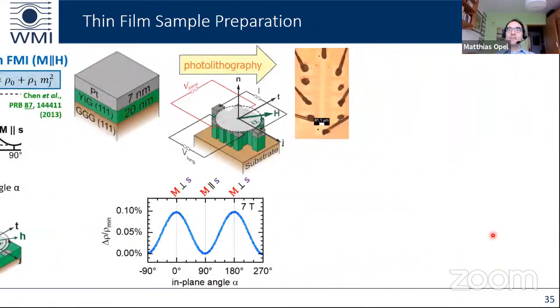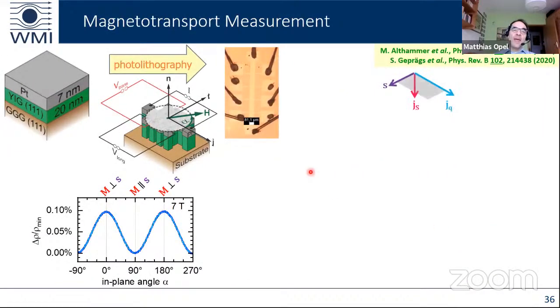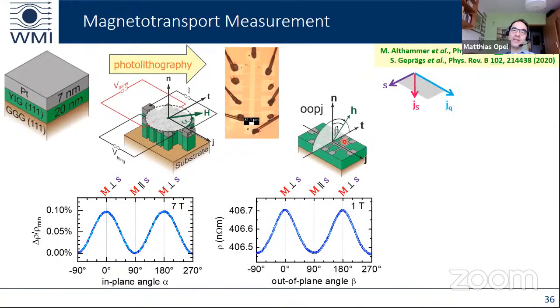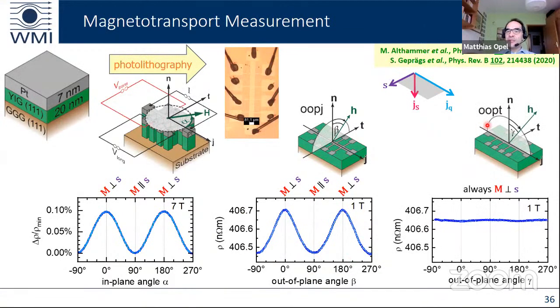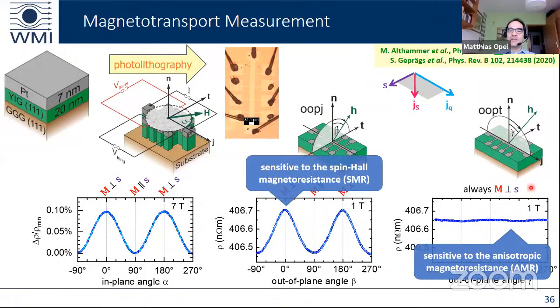Now, we can also rotate the magnetic field not in plane, but out of plane, perpendicular to the current direction, and we see the very same. We can apply the magnetic field out of plane perpendicular to the transverse direction, and there we see nothing. We just see a constant resistivity, because here the magnetization is always perpendicular to the spin polarization S.